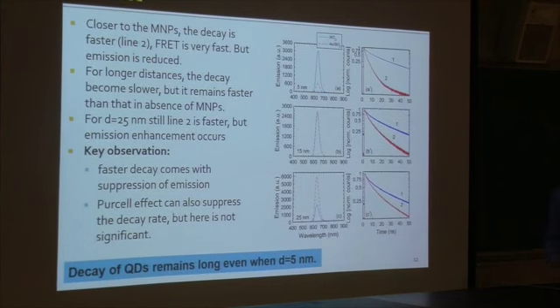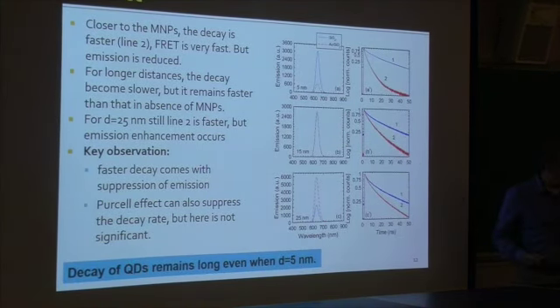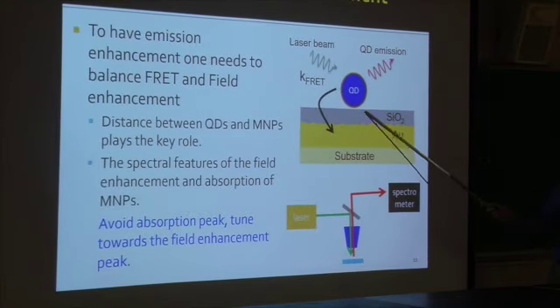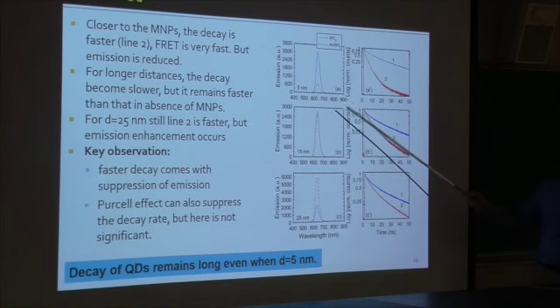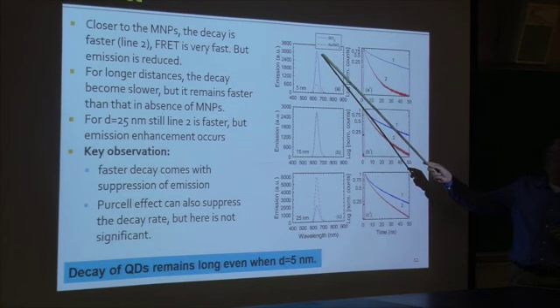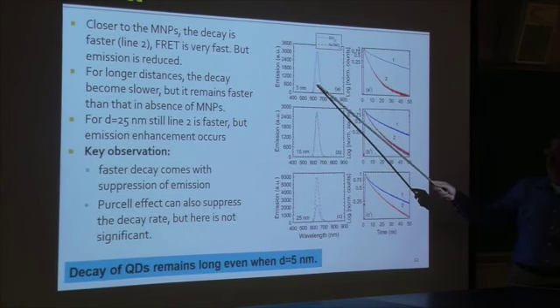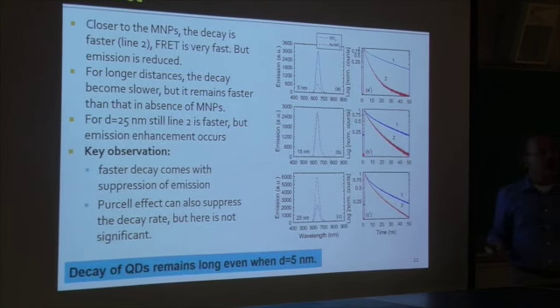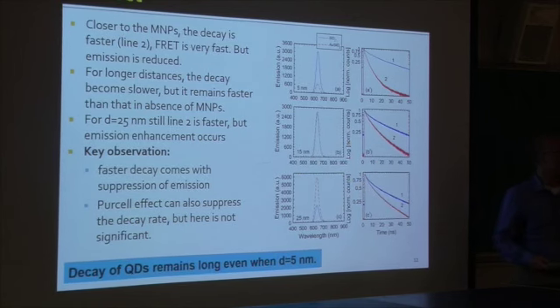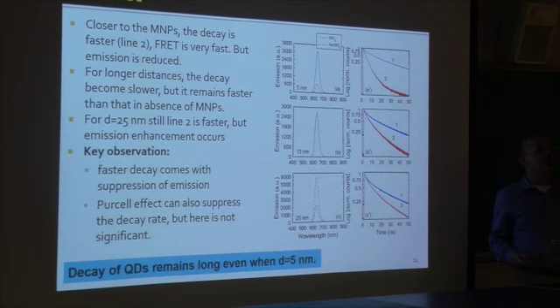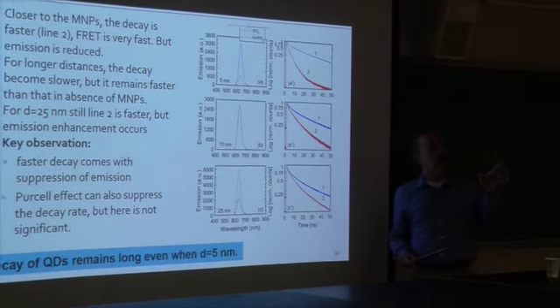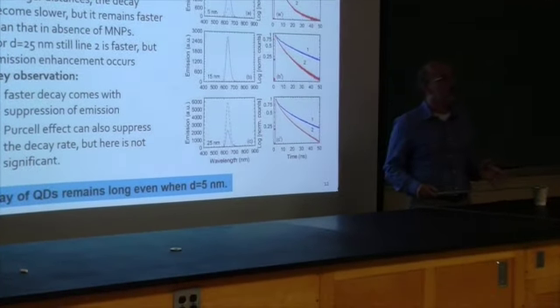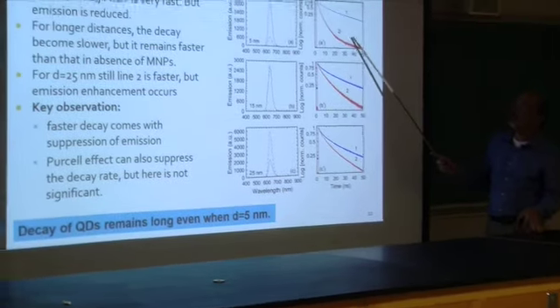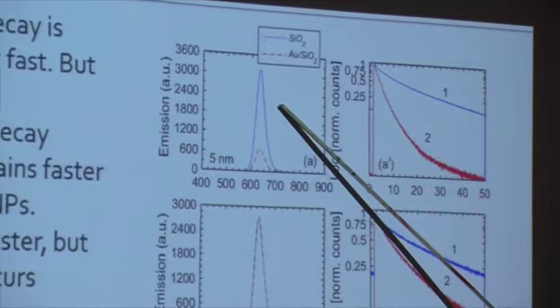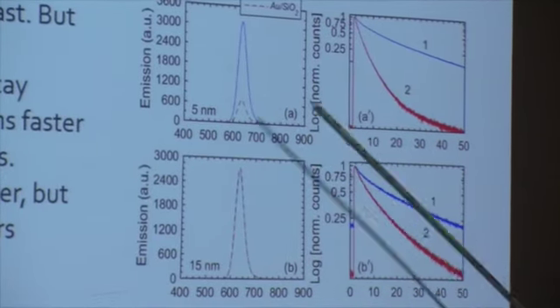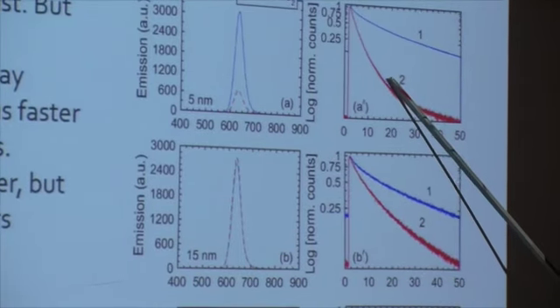This is nothing new. Everybody knows that. Here is the deal. When the thickness of the silica is about 5 nanometers, this is the emission of the quantum dot on the silica, and this is the emission of the quantum dot on the silica and gold. You can see that you don't actually have enhancement. You have much less emission. This is because, although you have a good amount of field enhancement, the emission of the quantum dot goes very efficiently towards the metallic nanoparticle. And if you look at the lifetime, this is the lifetime of the quantum dot on glass, and this is the lifetime of the quantum dot on glass with gold underneath it. You can see how fast it decays.